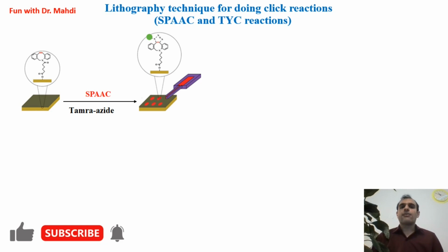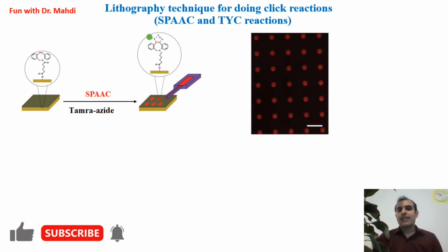And we need to leave it for 1 hour. And after 1 hour, we need to wash it. With water, we wash the surface. And now you need to take a photo with a fluorescent microscope, and we will have something like this. You can see the red dots on the surface. Red dots, these are TAMRA azide. When we have TAMRA azide on the surface, it means the click reaction between azide and alkyne has taken place. And the click reaction was successful.